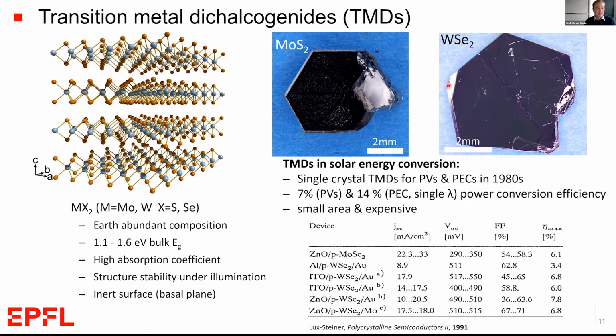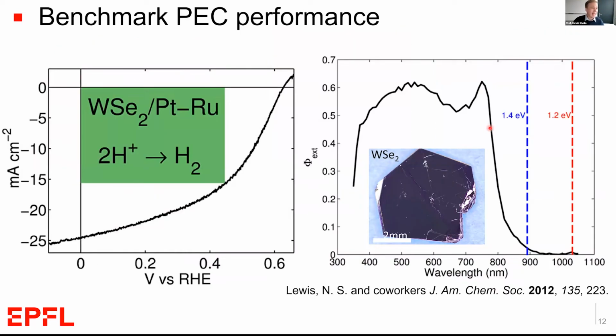Nevertheless, more recently, Nate Lewis's group at Caltech, and I showed this graph already before, demonstrated that this tungsten diselenide can be an excellent material for hydrogen evolution, giving this photocurrent of 25 milliamps per centimeter square, compared to only about 8 milliamps that we were getting in the best case with the CIGS. This material is performing a lot better. And I just want to point this out because it'll be important for later.